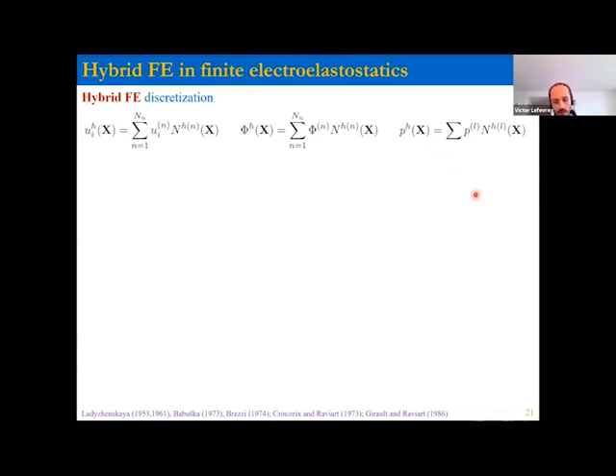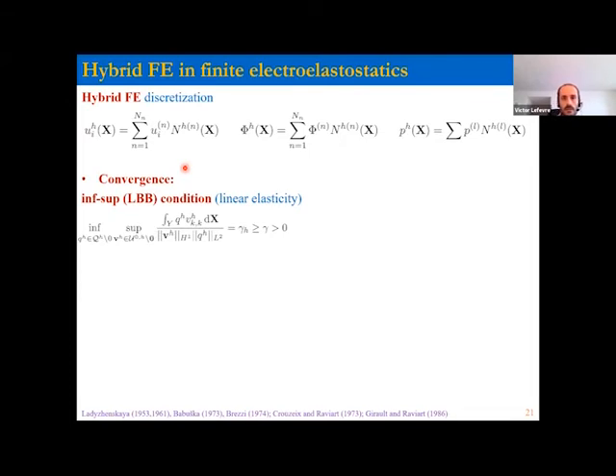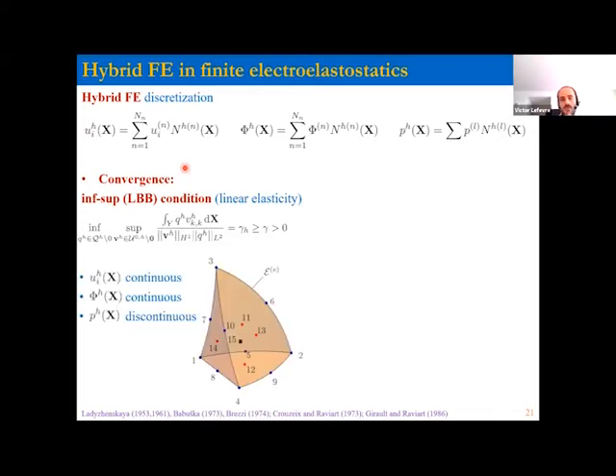It's well known that for incompressible materials, you need to be careful about the choice of discretization for the pressure and for the displacement field, if you want the scheme to converge to the exact solution. In particular, in the context of linear incompressible elasticity, there's the famous Ladyzhenskaya-Babuška-Brezzi condition. That's for linear elasticity. And so what we did was to use an element essentially designed for Stokes flow. Stokes flow is analogous to linear incompressible elasticity.